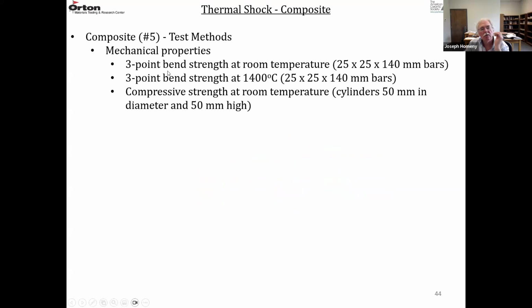So they measured 3-point bending strength at room temperature, 3-point bending strength at 1400 degrees C, so it's a hot modulus of rupture, and compressive strength at room temperature. The bend bars are typical sizes, 25 by 25 by 140 millimeters. The compressive strength is measured on a cylinder, 50 millimeters in diameter and 50 millimeters high.